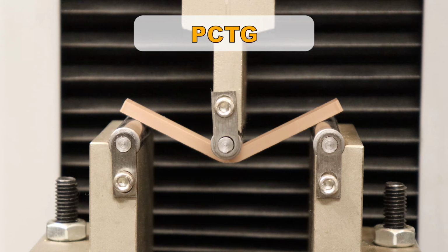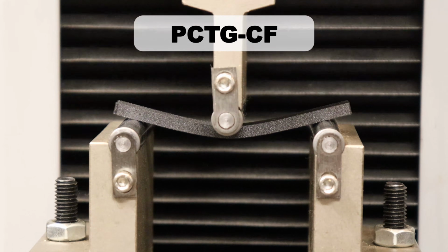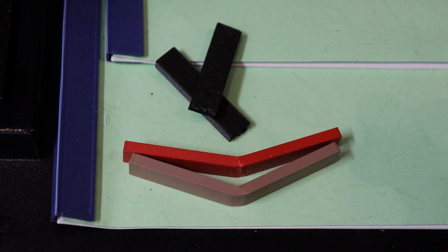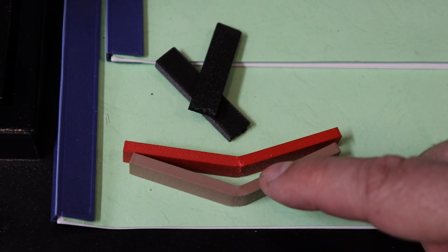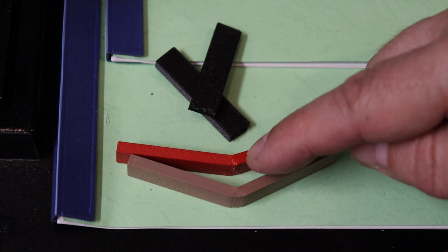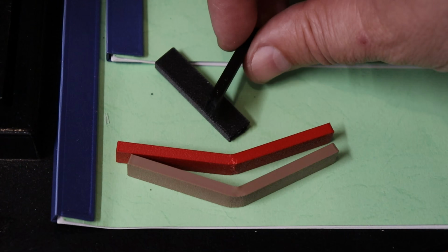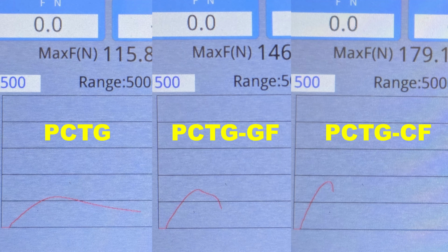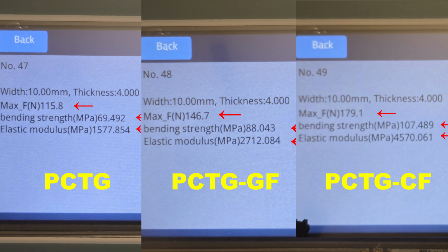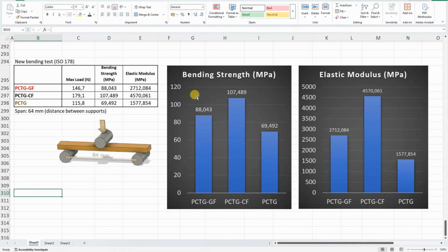Another bending test, no fiber version, glass fiber, and CF version. This describes these materials well. PCTG: biggest deformation, no break; smaller deformation before the failure on the glass fiber; and carbon fiber broke. Even these graphs tell us a lot about these materials. The force in function of time or deformation, maximal load, bending strength, and elastic modulus. Similar order we already saw with the previous bending test. The strongest is the carbon fiber version in both bending strength and elastic modulus, second the glass fiber version, and the weakest between these three is no fiber PCTG.